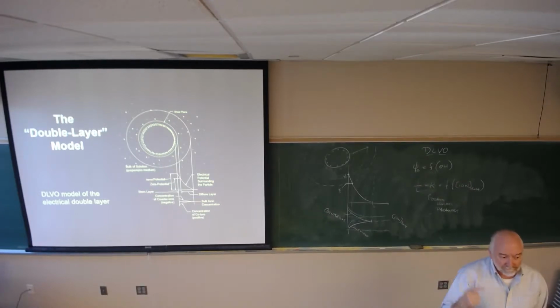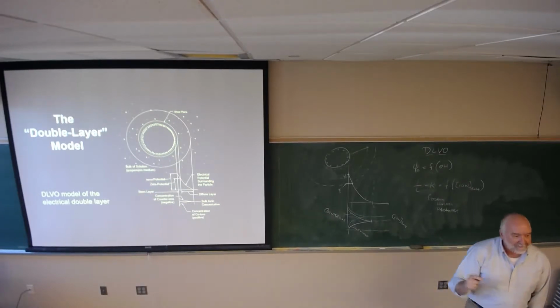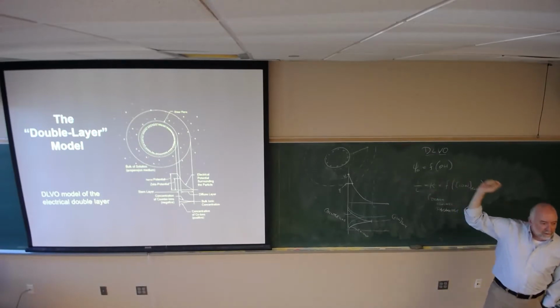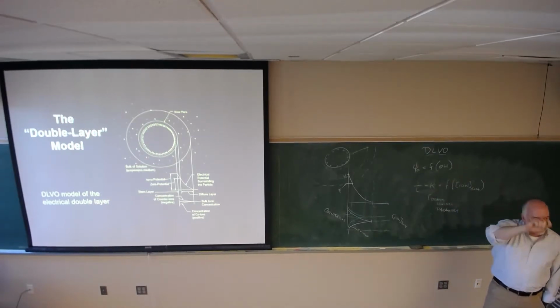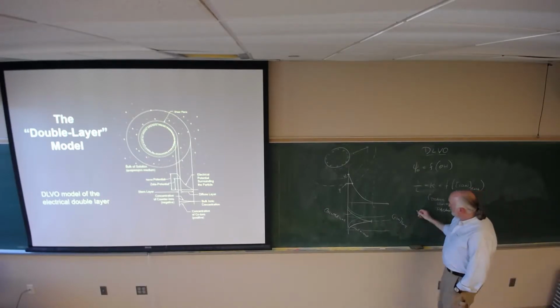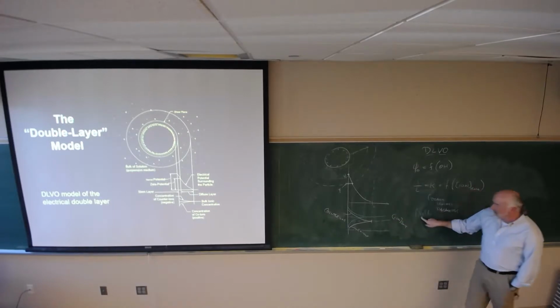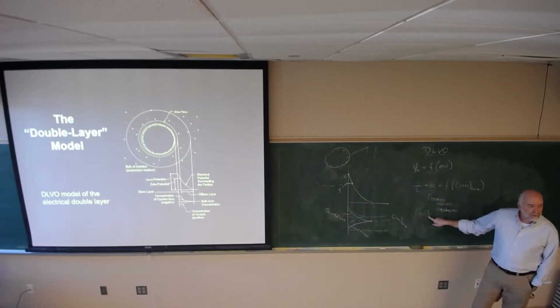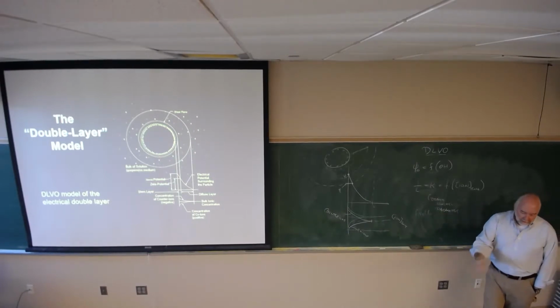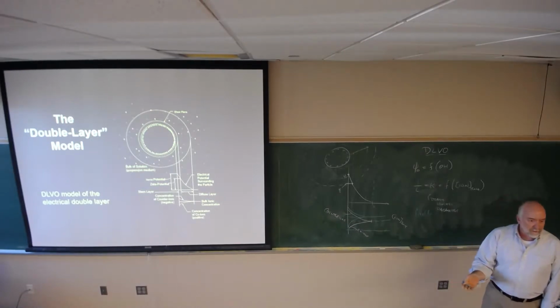Add more particles. Add more salt. This is all independent of the number of particles in the system, so that's good too. You add salt. If I increase the concentration of sodium chloride, I bring in a +1 sodium and a -1 chloride, no change in pH. It's very easy to demonstrate that. Go in the lab, get a pH meter, put water in a beaker, add salt. Nothing should happen with pH.